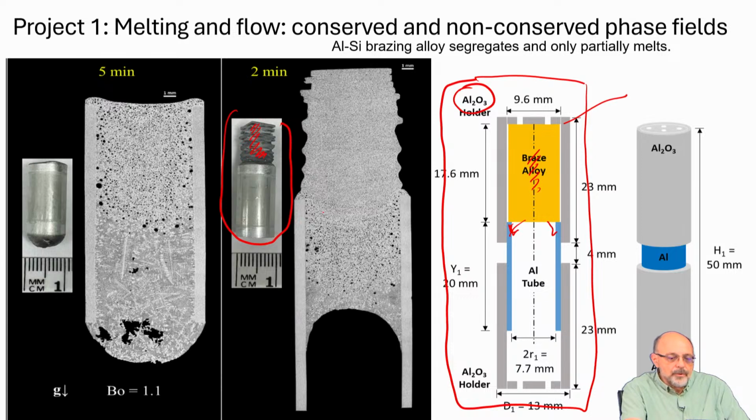Okay, so this melts, and this is a short time. This is longer time results. Melts, and then you cool it off, and it's solidified. So what happens? Why am I getting this standard dendritic solidification here, while here I'm getting something that looks like spherical pores and tiny white spherical grains? Why am I getting such a different microstructure?